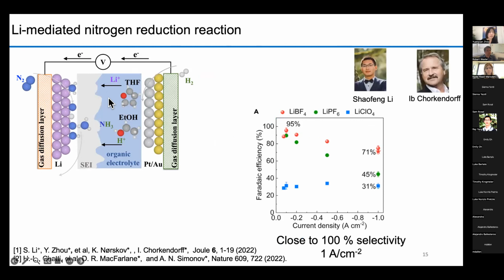The non-aqueous solvent THF contains lithium salts and the proton shuttle ethanol. Once the reaction starts, the lithium cation is electrodeposited on the cathode surface, and the metallic lithium is very active, decomposing the organic solvent and forming a solid electrolyte interface layer. This is a concept which we borrowed from the lithium battery.